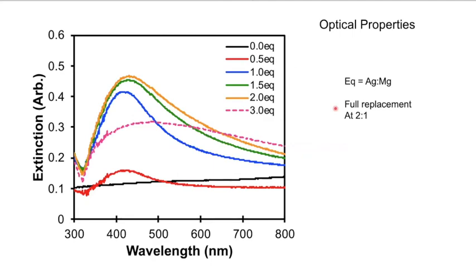Same thing, right? We can track, and this time is with stoichiometry, we can track the optical properties. And this is for silver. You would get a full replacement at 2:1 or at 2 equivalent. And indeed, in the extinction spectrum, this is when the silver plasmon is the highest. If you overdo it, then everything kind of crashes out of solution. So at 3 equivalent, everything is replaced.